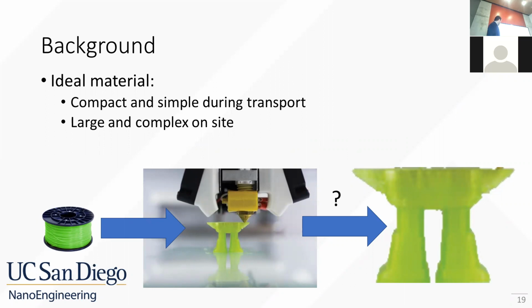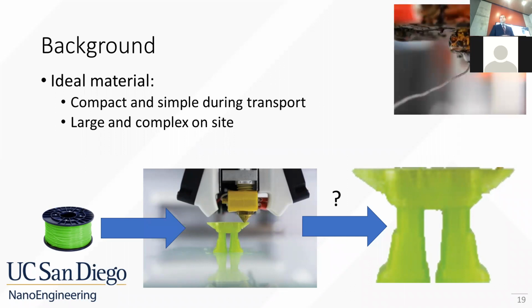So in this example, I show an FDM filament that you're printing using a small 3D printer, and you expand it to make a larger part. There's already an FDM filament with these sorts of properties. It's called ColorFab Lightweight Foam PLA, and it's an FDM filament with a blowing agent that's incorporated into the filament, and it expands upon heating.